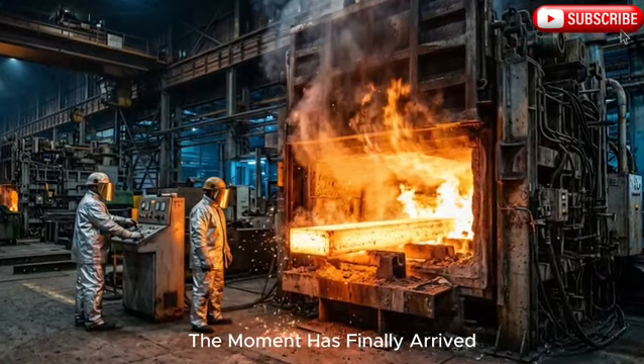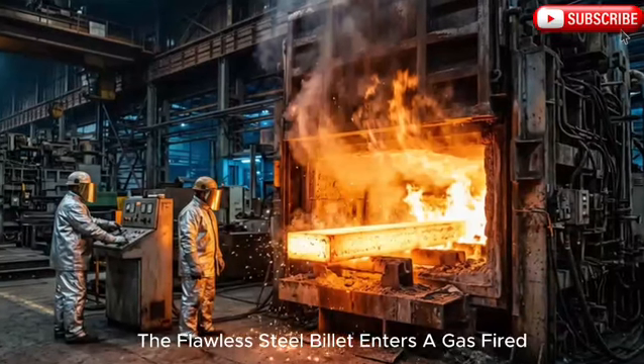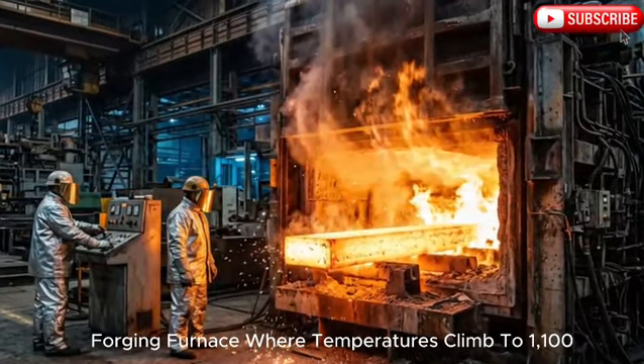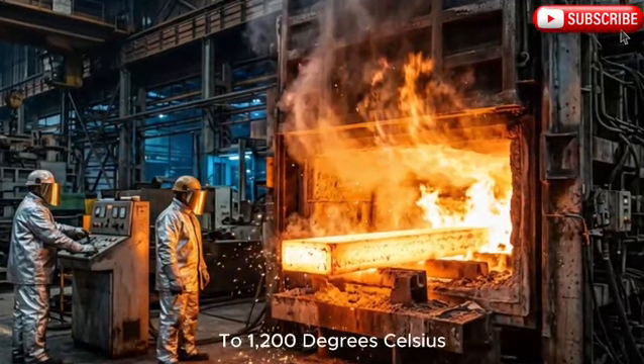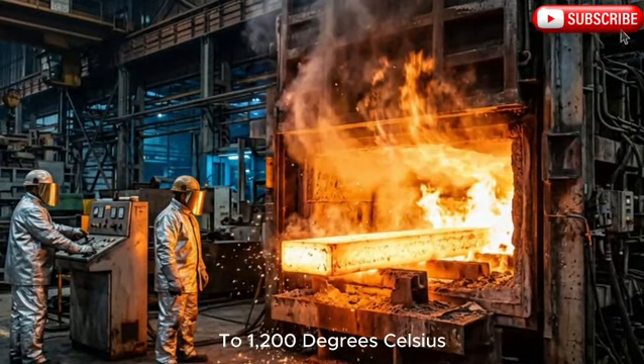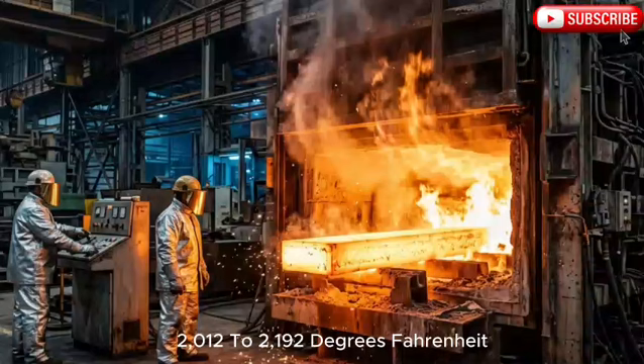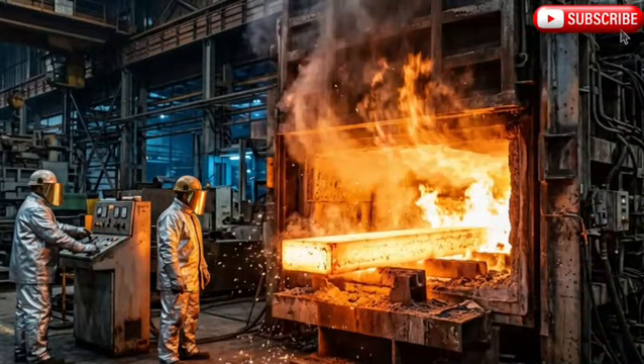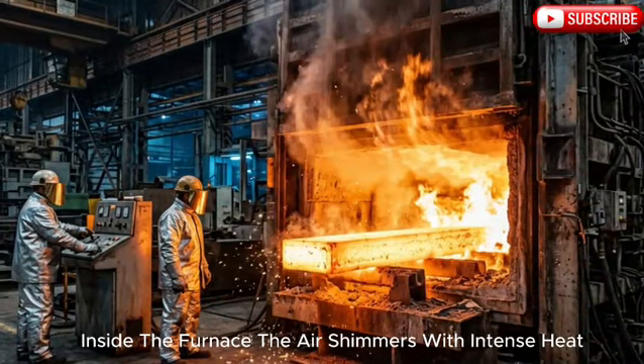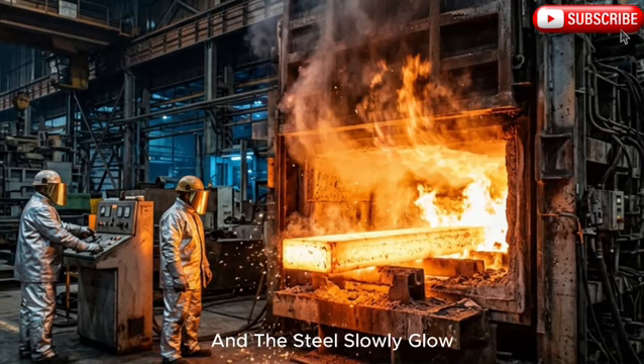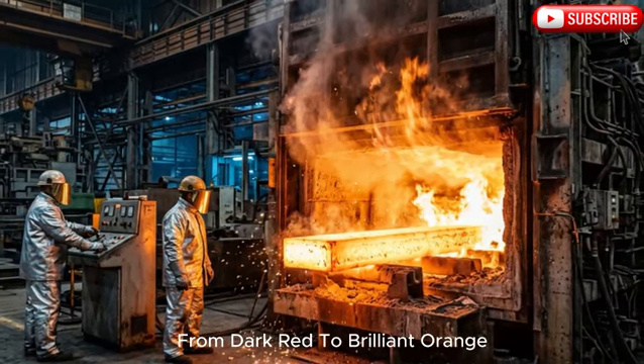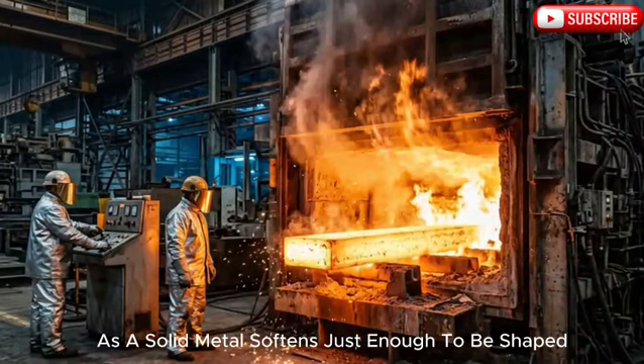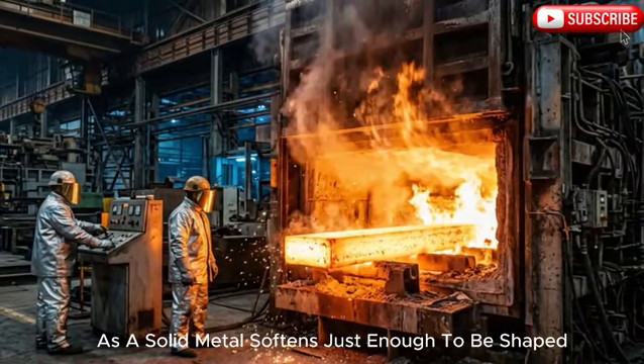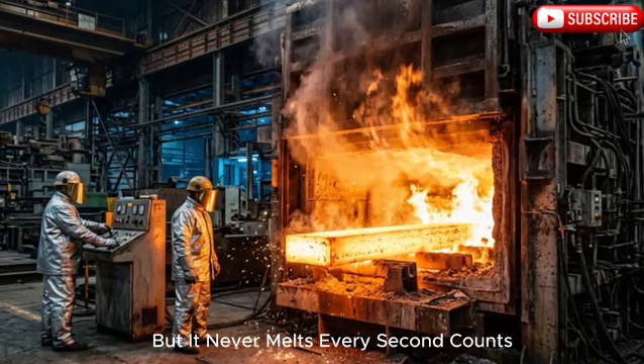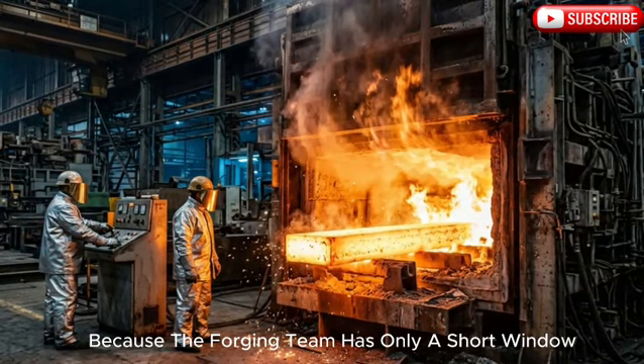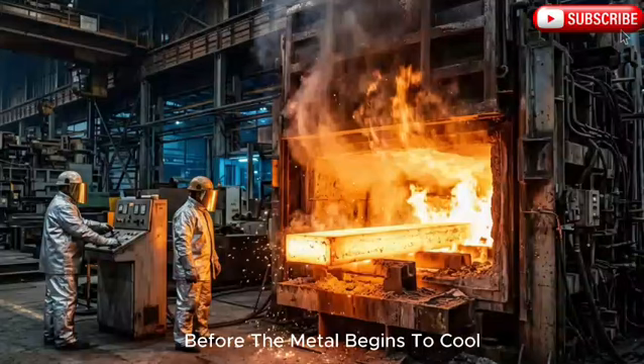The moment has finally arrived. The flawless steel billet enters a gas-fired forging furnace where temperatures climb to 1,100 to 1,200 degrees Celsius, 2,012 to 2,192 degrees Fahrenheit. Inside the furnace, the air shimmers with intense heat, and the steel slowly glows from dark red to brilliant orange. You can hear the roar of powerful burners as the solid metal softens just enough to be shaped, but it never melts. Every second counts, because the forging team has only a short window before the metal begins to cool.